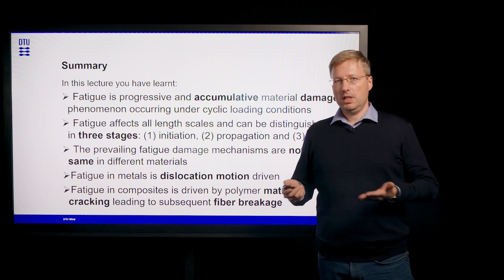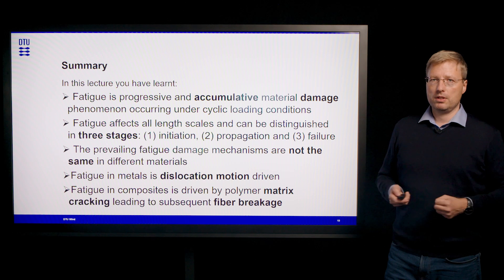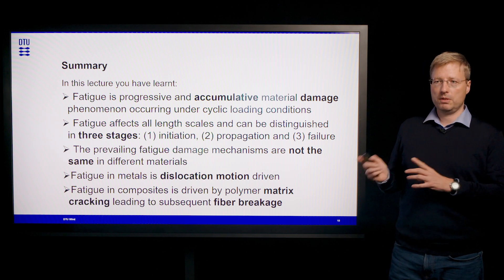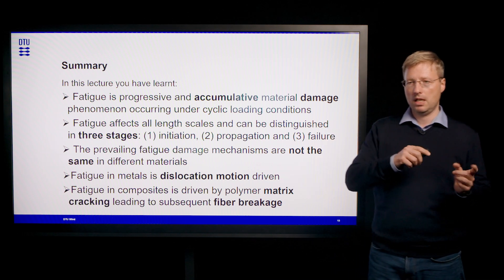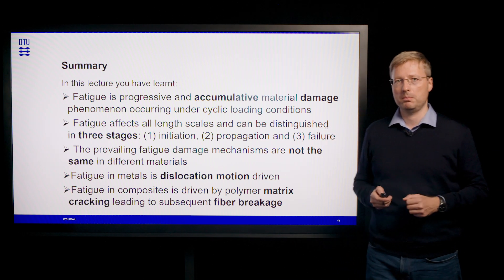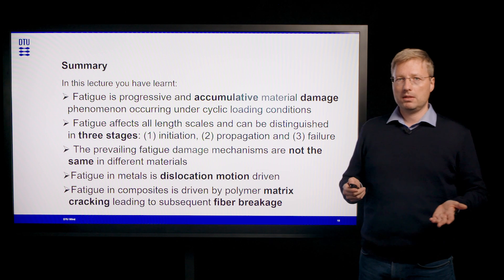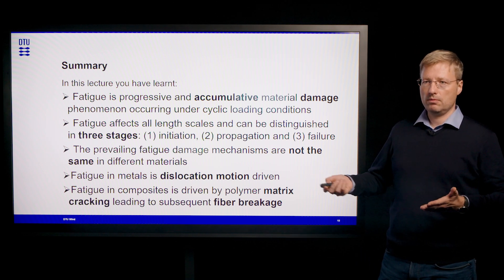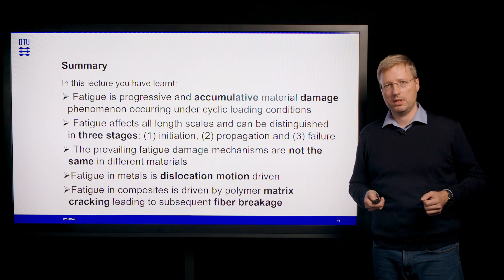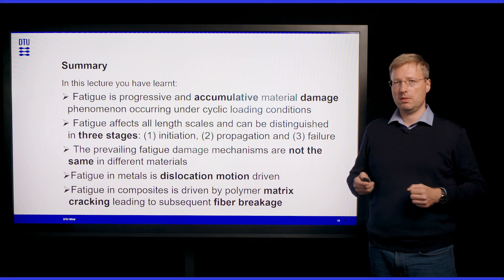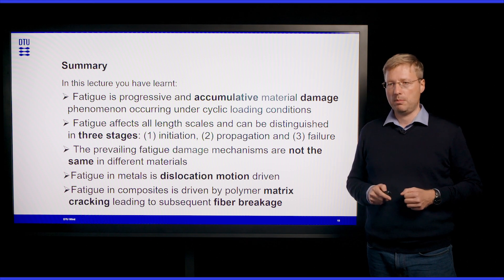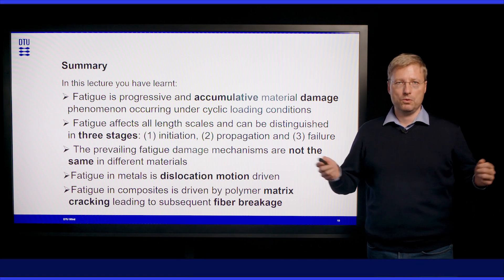The prevailing fatigue damage mechanisms, and that's important, are not the same for different materials, as we have seen. There is a huge difference between metals and composite materials, for example. Fatigue in metals is dislocation motion driven, whereas fatigue in composite materials is driven by polymer matrix cracking, leading to subsequent delamination and fiber breakage. Thank you.